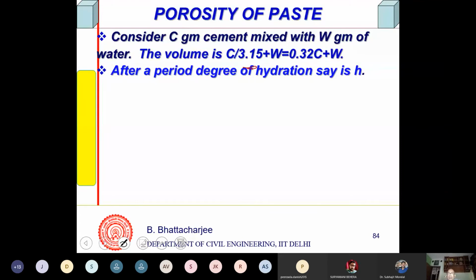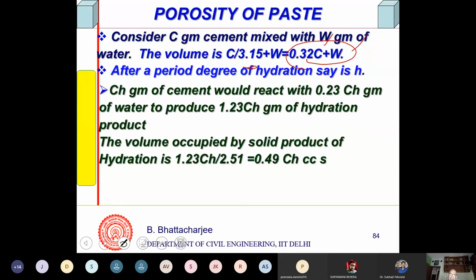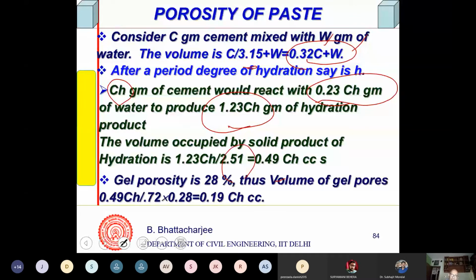Specific gravity of cement is 3.15. So this will be the original volume if cement is C and W is the amount of water. And some of it will hydrate. The proportion of hydration is called the degree of hydration. So CH gram of cement will react with 0.23 CH gram of water and produce this much hydration product. The volume occupied will be this much, and of the original volume, 28% is gel pores. So if you multiply it by 0.28 and so on, you get the gel pores.